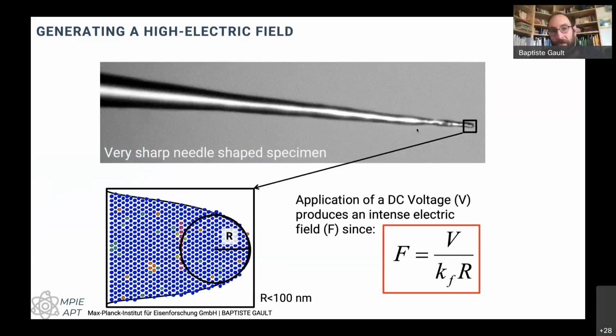It can be quick, and once you have a needle that is good enough, you can run it. If it breaks down, you go back and you can resharpen it within minutes, and then you're just 10 microns down the shank, and you can keep doing it and doing it. So you don't necessarily need 10 sessions on the FIB to get quite a lot of data.